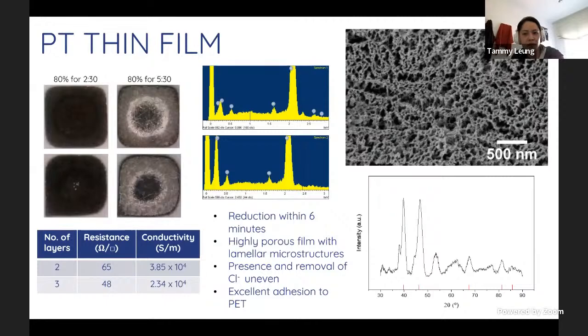showed reduction within 6 minutes using the oxygen plasma and had conductivities up to 10 to the 4 Siemens per meter. Under SEM observation, we see that the film itself was highly porous and showed a lamellar microstructure. The porosity is attributed to the removal of the chlorine ions, which, when comparing the gold and platinum, shows 1.5 times more chlorine. So this roughness that you can see on the surface contributes to the appearance of the film as well as the lower conductivity.